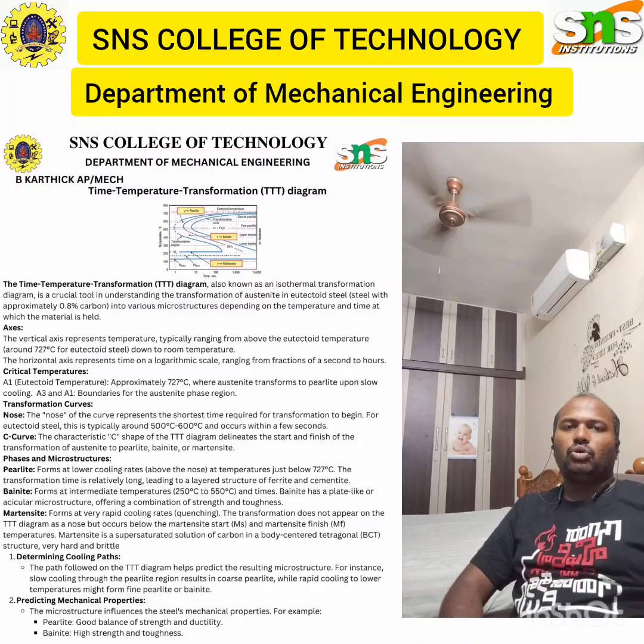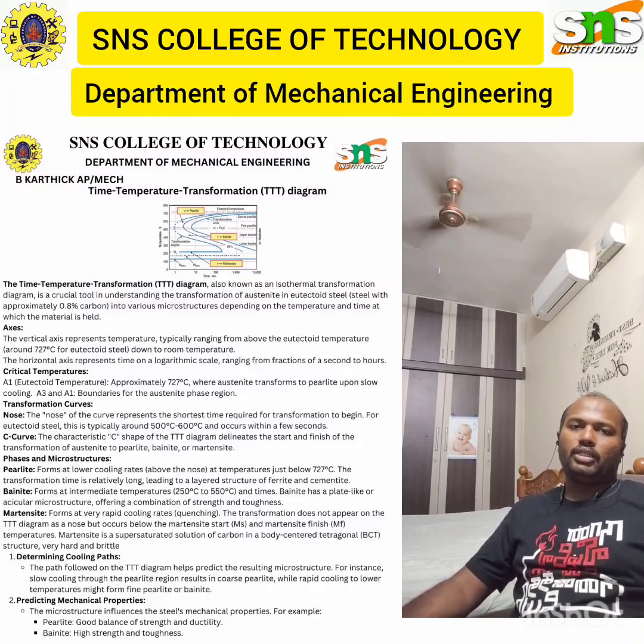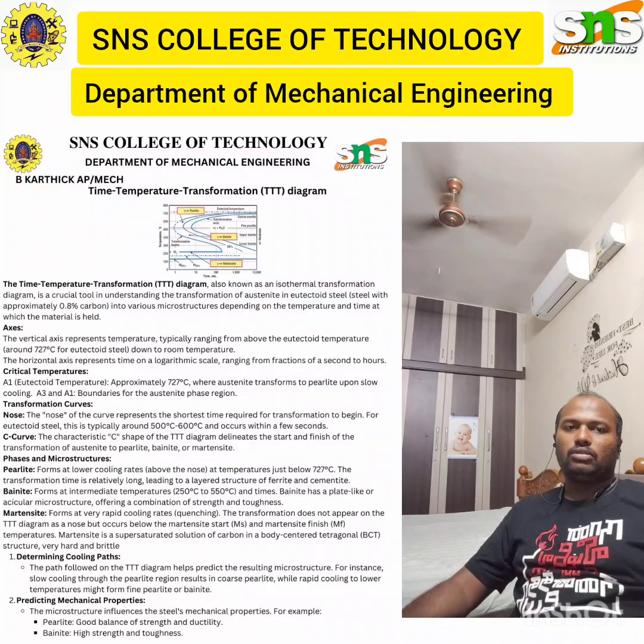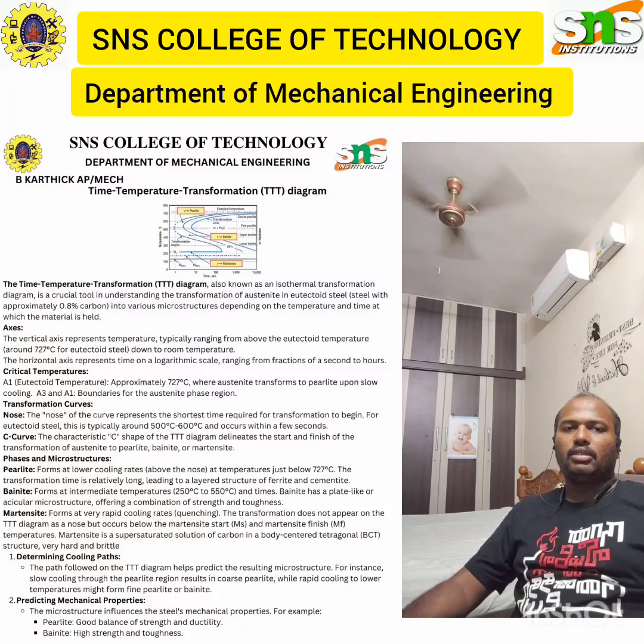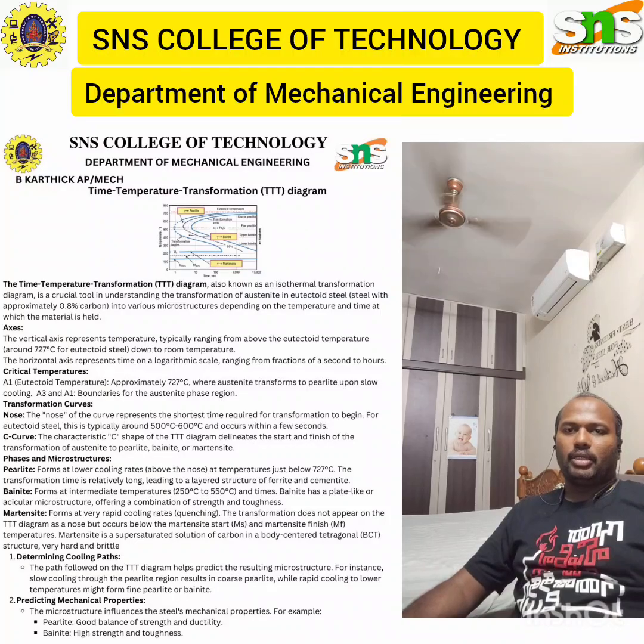In transformation sequences: cooling to 600°C, above the nose, and holding transforms austenite to pearlite over a few seconds to minutes, resulting in a coarse pearlite structure. Cooling to 400°C, below the nose, forms bainite over several minutes to hours, providing a combination of strength and toughness. Quenching rapidly to below the Ms temperature forms martensite, which is very hard and brittle, often requiring tempering for practical application.